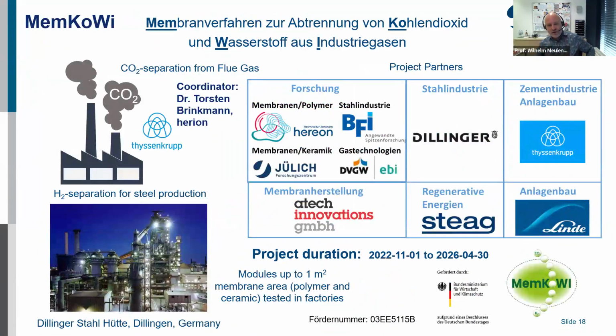So I have to mention also that we have here a very large project running in Germany, coordinated by our colleagues from the polymer membranes in Hereon, which is also a Helmholtz organization, coordinated by Thorsten Brinkmann. And the idea is here to test the membrane modules on a flue gas in a cement plant at ThyssenKrupp Polysius in Beckum. That means we want to install a few square meters of polymer membranes in the flue gas stream of this plant, and look how much CO2 we can separate. And in addition, we will also test a small module of half a square meter or up to 1 square meter from the ceramic membranes.